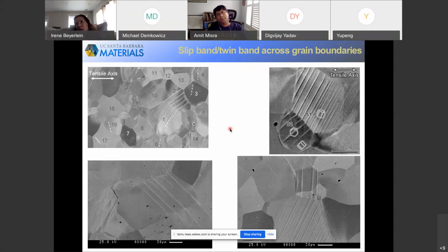So one can imagine that if I have different types of plastic behavior in different crystals, different materials, every material would have its own critical spacing between twins. It's also very critically dependent on the amount of twin shear for that particular twin. So that would engender a different critical spacing for different twin modes.